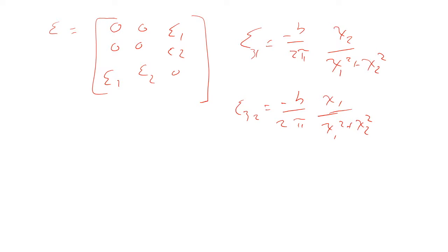Right, so we have a form that looks like this. So the strain depends on the absolute position, x2 and x1, right? But decays with the square of the distance, right? So at large distances, the strain goes to 0, right? And then at short distances, it becomes undefined, right? So that in the middle there, where it's undefined, causes a problem when we want to calculate energies, right?